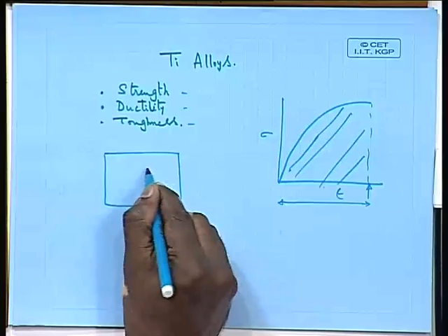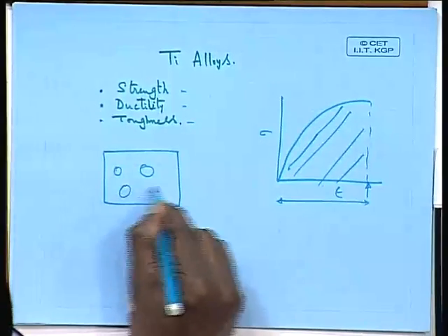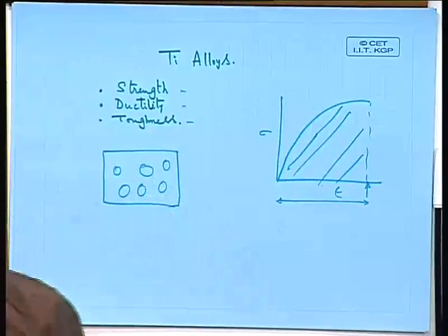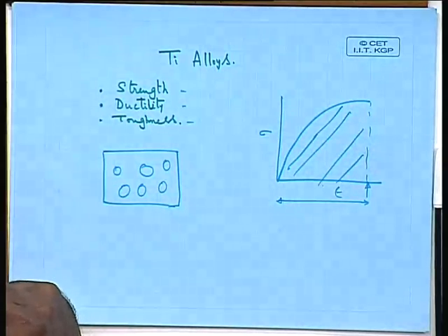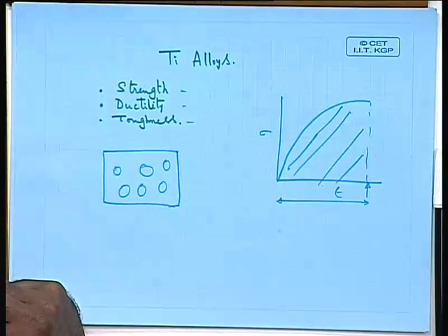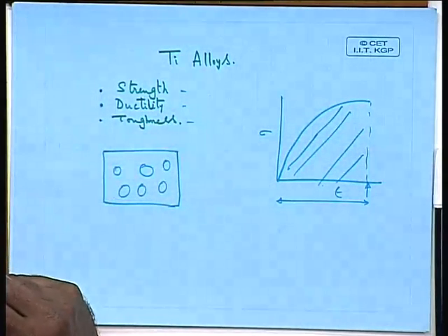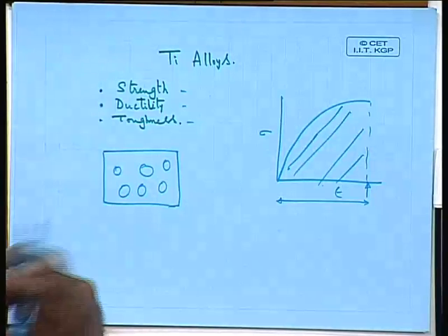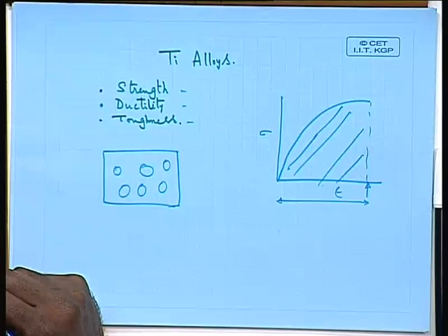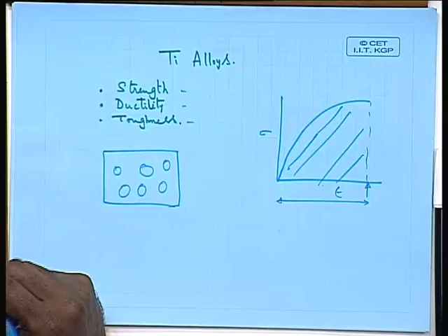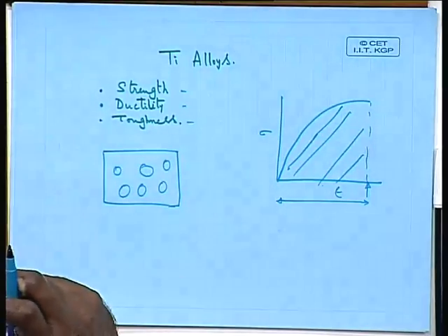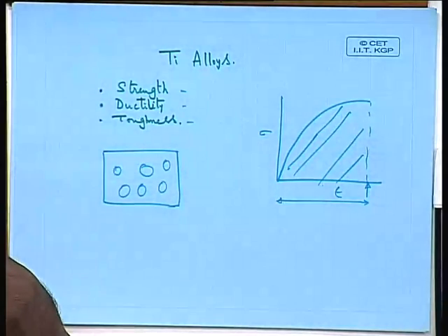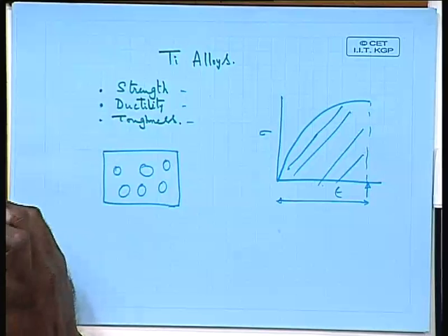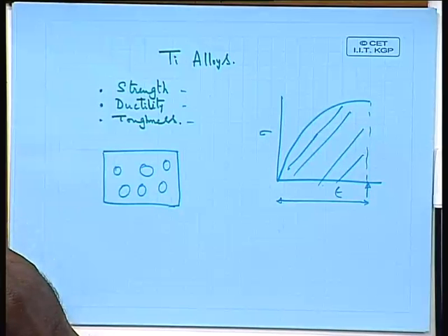If you have a microstructure of beta in which you have alpha as this kind of spherical particles, let's say, or some kind of more or less spheroidal particles, in this kind of material, if you look at the mechanical properties, you will have a good strength because it is the two-phase mixture. Whenever you have a two-phase mixture, you get good strength. This is known to us.